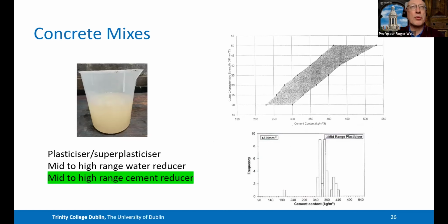But when it comes to cement, which is what we're interested in reducing so that we can reduce the carbon footprint, when we look at a similar graph for cement contents on the top right-hand corner, you can see there's variability there. And if you look below, you can see that there's quite a lot of people making 45 megapascal concrete with high quantities of cement. And one wonders whether or not we could use, for example, plasticizers, if they're not already using them, or perhaps better quality control, more careful quality control, so that we achieve the target strength with a smaller quantity of cement. We shouldn't allow a free range, use as much cement as you like. And indeed, very often we put a limit on cement content for cracking purposes, thermal cracking purposes.